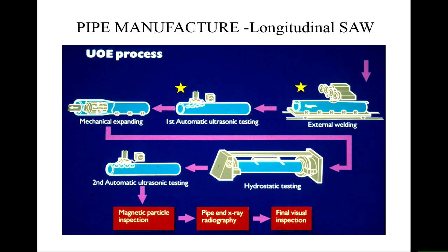So the failure rates after these processes are very, very low. And they're usually for something that you didn't even consider during the manufacturing process. So you hope that you control it. So generally, if there's a failure of a pipeline, it's not a failure of the actual pipe segment itself, it's a failure of the welds between segments.